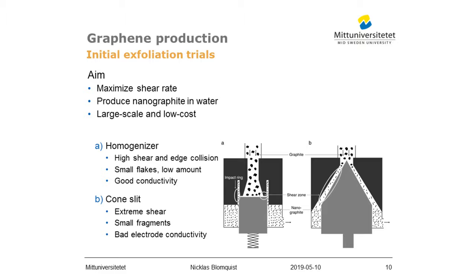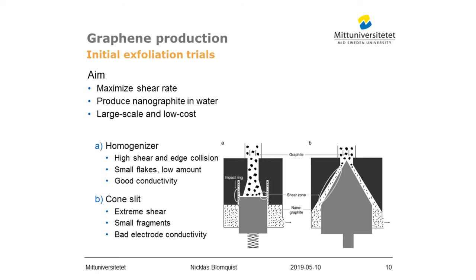Our initial tests were with a commercial homogenizer, and you can see the shear zone of that here. This shear zone had a high shear, but also high edge collision. So the particles, or the flakes, were very small, but we only had a low amount of thin flakes. The material we got here had a good conductivity, but we wanted thinner flakes and we wanted a bigger surface area of the flakes. We then developed a cone slit shear zone, which looks like this.